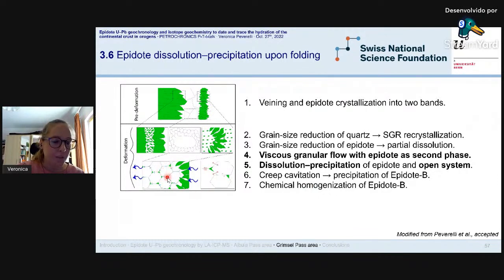The sliding of quartz grains relative to each other produces creep cavities in which epidote B can precipitate. And this dissolution-precipitation process is repeated enough times to cause the chemical homogenization of epidote B. And the precipitation of epidote B along quartz grain boundaries is responsible for keeping quartz grain sizes small in a process that we call viscous granular flow.